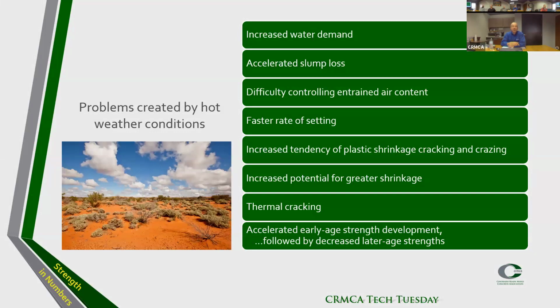Problems that may be created by hot weather or hot concrete: increased water demand, accelerated slump loss. So you batch at the plant, you drive out 45 minutes, 60 minutes, you might have quite some slump loss, especially at hot temperatures. It's more difficult to control the air in hot concrete. Set times are much faster.